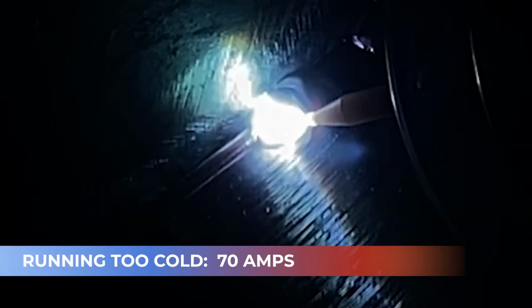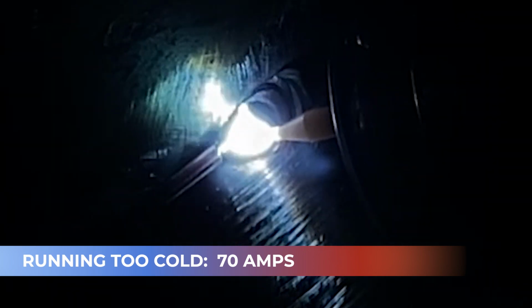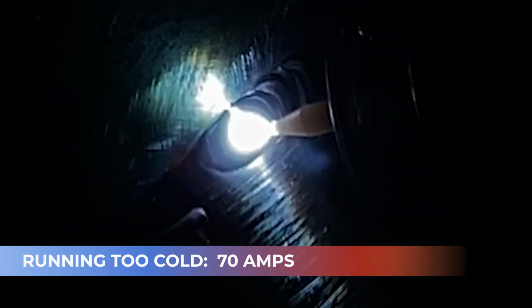All right, y'all. So as you can see here, based off of my puddle, I'm running way too cold. This is on the 12 gauge. I'm running 70 amps, 3/32 filler. And you can tell by watching closely that the base metal is not being consumed into the puddle. I'm really having to stop and pause and wait for the metal to be consumed. It's not wanting to flow. I'm having a hard time feeding wire into it. It's a telltale sign, 10 times out of 10, that you're way too cold. You need to crank that up about 10 amps and see what happens from there.